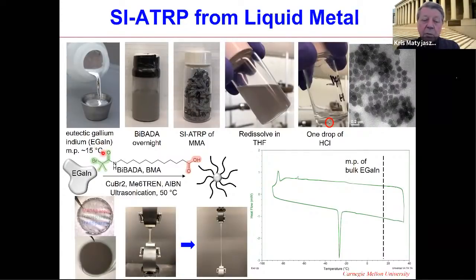And then you can disperse it by ultrasound in a solvent and use this BIBADA initiator with a carboxylate group, which can anchor to the surface. And then you have the corresponding bromoamide to grow, for example, polymethyl methacrylate or polybutyl methacrylate, which will become a very elastic material. You can very easily disperse it, and then adding 1 drop of HCl, you separate it again, and the size of particles in a dispersed state is in a range of approximately 100 nanometers. They are so small that they become transparent, in contrast to material which is built on a macroscopic structure.